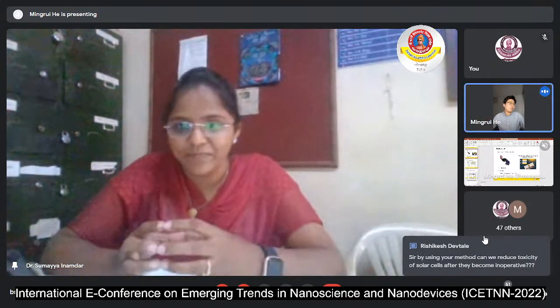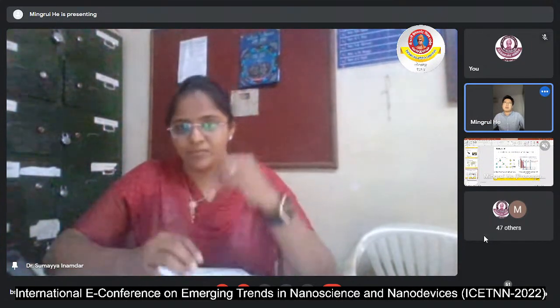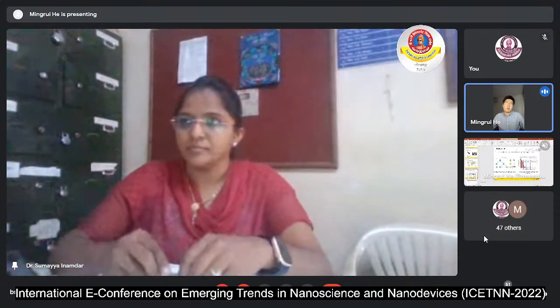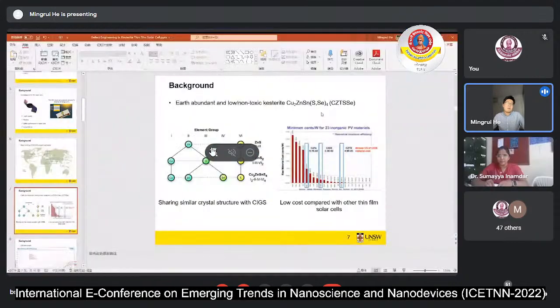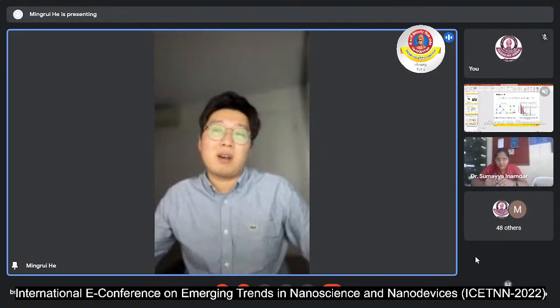Currently, the CZTS materials can be pure sulfide, pure selenide, or mixed sulfide selenide. The baseline of pure sulfide, without selenide, can achieve beyond 10%, with a higher VOC of around 800 millivolts, and that's why we haven't published that paper so far. For pure selenide, our baseline is around 11 something, and sometimes we can achieve beyond 12%. For the mixed sulfide selenide, we haven't started that experiment yet, but probably we can achieve between 11 and 12%.